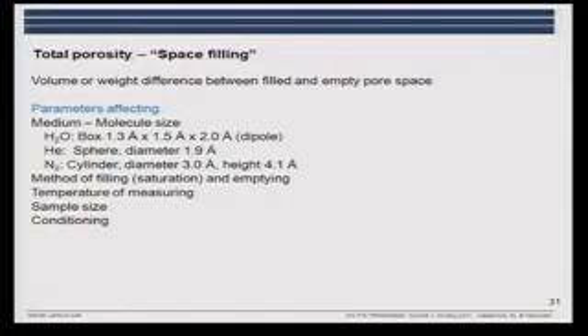The temperature you measure at, the sample size, are you actually able to penetrate the full sample? And again, how have you conditioned your sample before you start to do this test? For the nitrogen, you have to have the water out before the nitrogen can enter, and also for the helium. So you have to dry your samples in a way.